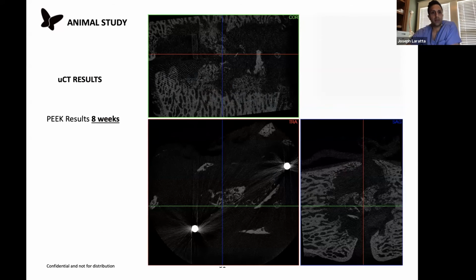When we look at the MicroCT results of PEEK at 8 weeks, this is one of the end plates here. This is another one of the end plates here. You can see that there's still some fragments of the iliac crest bone, but there's actually no integration of bone across the cage or around the cage. And if you look at the bottom right, this is kind of a remarkable picture. You can actually see that there's relative osteolysis around the cage,